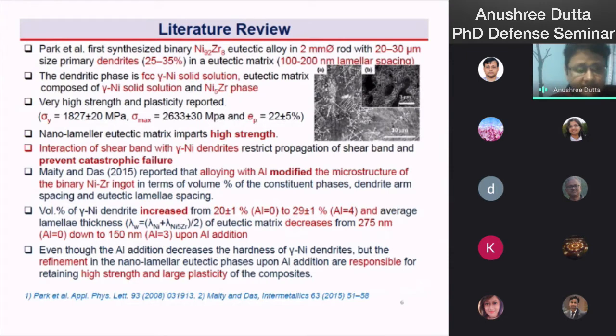In 2015, Maity and Das reported that alloying with aluminum modified the microstructure of the binary nickel zirconium eutectic in terms of the volume percent of the constituent phases, dendritic arm spacing, and eutectic lamellar spacing. The volume percent of the dendritic phase was observed to increase from 20 to 29%, whereas the eutectic matrix was refined from 275 nanometer to 150 nanometer.